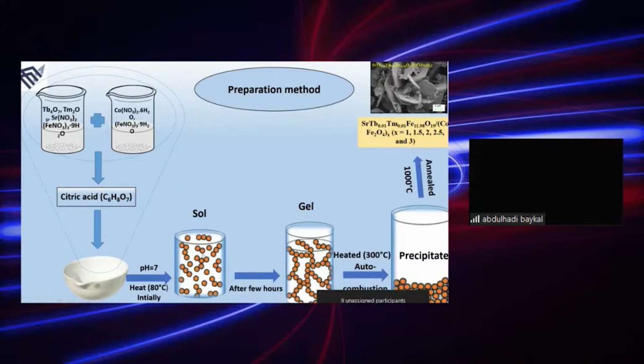The liquid is the solution. But when we continue to heat it at this temperature, I mean at 80 degrees, somehow precipitation will start, and then it means that the solution has already been converted into what? Into gel formation. Then immediately we will increase the temperature from 80 to 300 on average, and the auto-combustion within this to precipitate as it was given here. Then we will do the annealing process for this product.